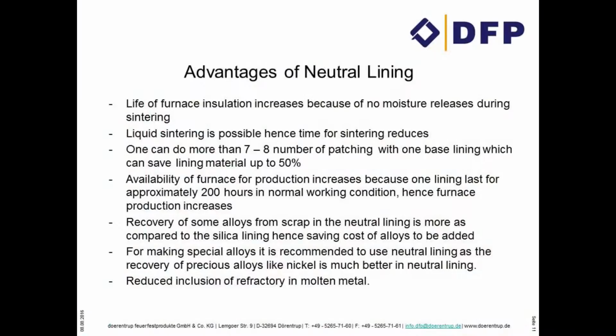Then the inclusions in the molten metal. Normally the erosion of the refractory goes into the liquid metal itself, and neutral lining has very little erosion. So the inclusions in the metal because of the refractory are less.